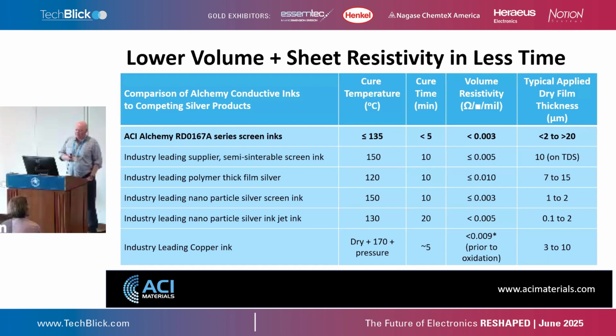So this is a look, and it's a little bit historical, at our Alchemy Ink series on top, curing at about 135 centigrade against other semi-sintering silver inks, against copper inks that require higher drying temperatures and some compression to get their conductivity. And it's really about getting that cure time down to use tunnel dryers and roll-to-roll dryers that are much shorter. So you really want a dwell time of 1 to 2 minutes. And going higher temperature with our inks, we can get that to that 1 to 2 minutes and very conductive. With this semi-sintering type technology and nanoparticle technology, you're getting to 3 milliohms per square.